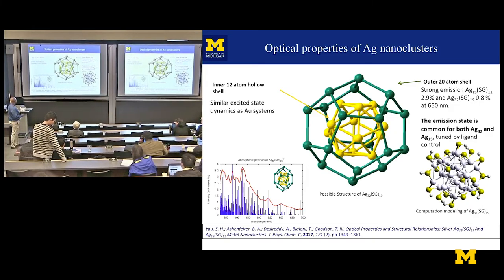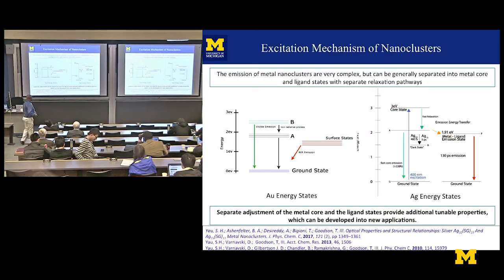And this also involved some calculations to find the properties of these systems, but we were still scratching our head. So we would like to go back to the drawing board and try to compare the gold 25 to what we see here. And so here are the gold energy states I just told you about, right? So there is some ground state and some visible emission. There's some surface state emission. So you have the core 13 atoms, and it's known now that the emission is coming from those outside staples, gold, sulfur, gold, sulfur, gold. All right? So there must be an energy transfer from the non-radiative processes to these surface states, which then is the emission that we observe in our spectrometer, okay? For the case of silver, it's completely different.